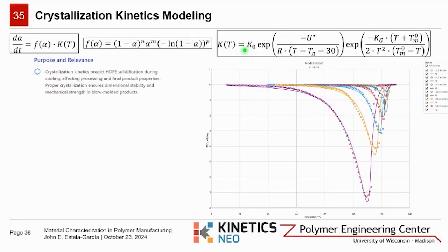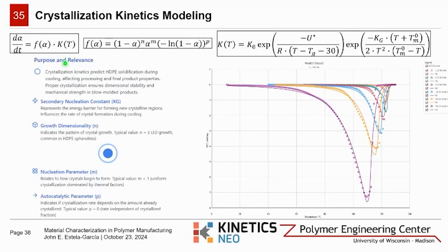So what happens is that this equation, the f of alpha equation, the Sestak-Berggren equation, is describing how the crystallization rate changes as more of the material crystallizes. And it includes parameters that indicate whether crystallization is uniform, autocatalytic, and how it's affected. And on the right-hand side here, the Hoffman-Lauritzen equation is describing how temperature affects the crystallization rate. It's providing insights into energy barriers that form new crystalline regions and how temperature affects the crystal growth.